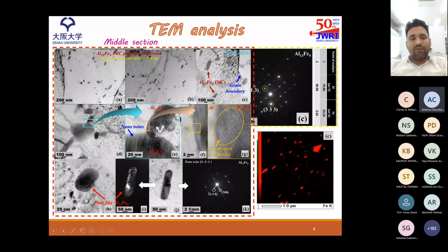Now, why have we observed these two types of morphology when the reaction is one? By TEM analysis we have identified that these elliptical shaped particles are precipitated out of the matrix, whereas these irregular shaped ones are the fragmented particles from the layers formed around the Fe particle. So that's why these two types of morphologies are visualized.